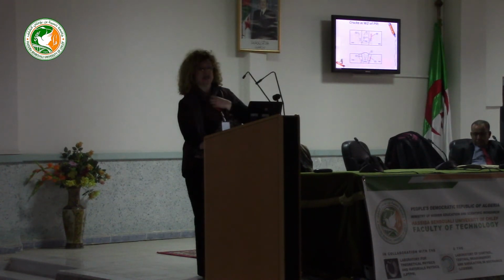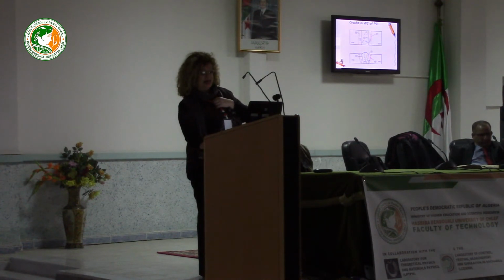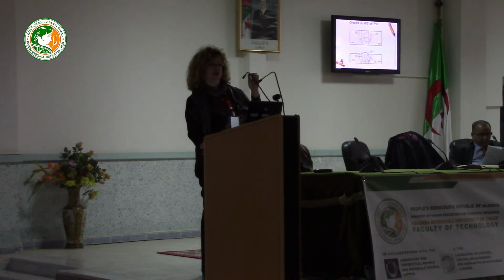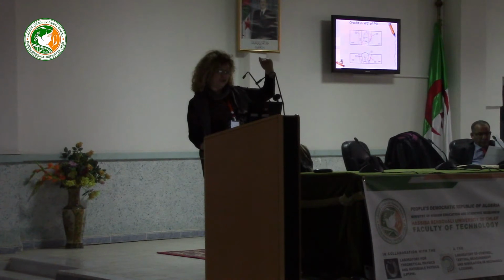What is very dangerous for us engineers are the cracks type 4. Type 4 cracks, here they are designated in red color, are extremely dangerous because they start in the heat affected zone, in the region of the heat affected zone which is called the intercritical region, and they penetrate into the base material.